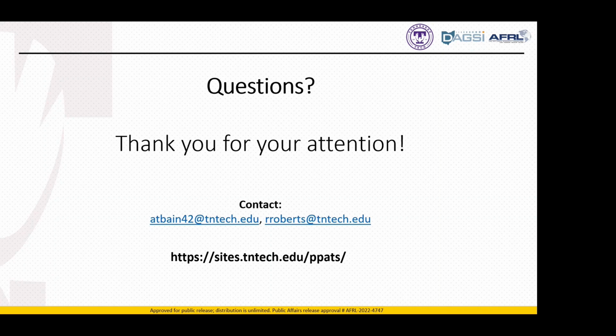Very nice presentation. You know, just to continue along Doug's lines, I think that what you're doing is extremely important for fuel cell degradation because one of the primary mechanisms of solid oxide fuel cell degradation is thermal stress related and cracking due to that. There's definitely some interdiffusion problems, but I think that those have been pretty well solved, and the very long lifetime of tubular fuel cells, where the interfacial stresses are lower, because you essentially have tubes which are allowed to expand and contract quite readily in most of those designs. They have very long lifetimes, over 20 to 40,000 hours. So I think that focusing on the mechanical stresses and thermal stresses which are induced is extremely important.